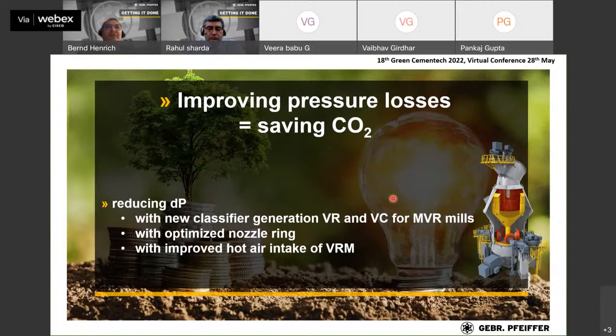We have made optimization on the nozzle ring, on the gas flow in the lower part of the mill, the gas flow in the classifier, and also the gas flow going to the system, then to the dust collecting system. That all has been done with CFD analysis, and not only CFD gas flow. No, two-phase simulation, powder to be considered in the gas flow.